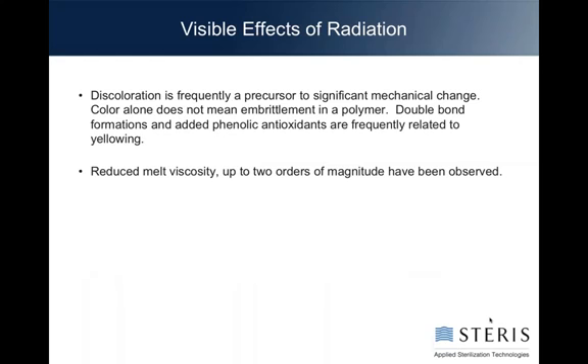So you're going to see the color, but while that's happening, know that at the same time, you're going to have these other events going on that will cause mechanical changes. For those of you who mold things, the melt viscosity will be significantly changed when it's irradiated. Up to 2 orders of magnitude have been observed. So there can be changes in how it will fill into a mold.